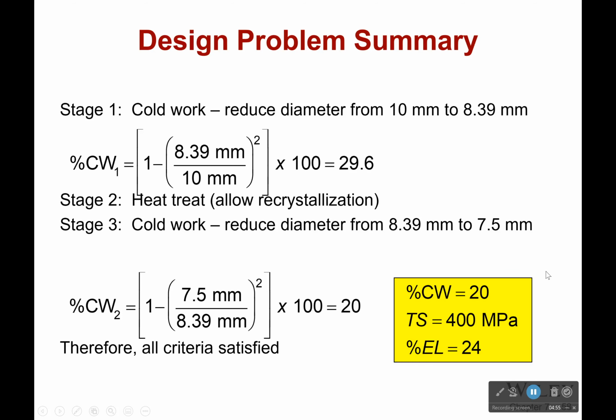So now we can finally show why this intermediate step is necessary. It's necessary because we need a percent cold work somewhere between 12 and 27%. However, to go from 10 down to 7.5, that's in the 40%s. So we have to do it in two steps. Our first step down to 8.39 millimeters is still going to be more cold working than we need. That's 29.6%, which is too much. So we're going to heat treat it and get rid of our cold work by recrystallization. We allow it to completely recrystallize. All of our cold work is gone.